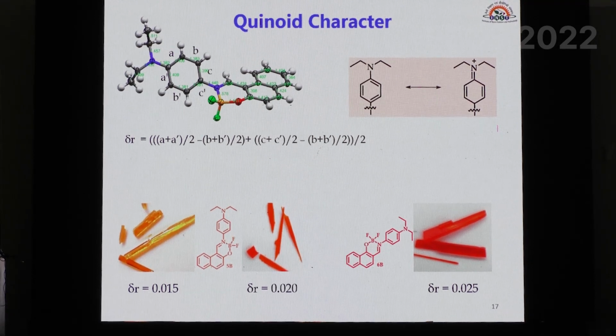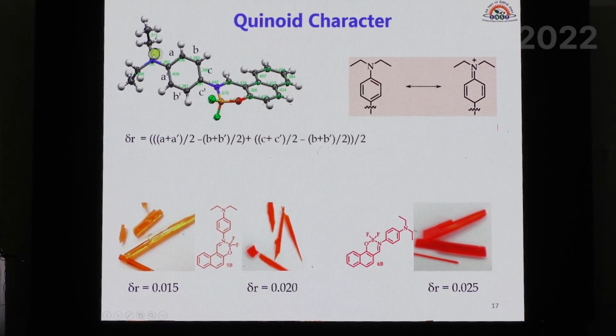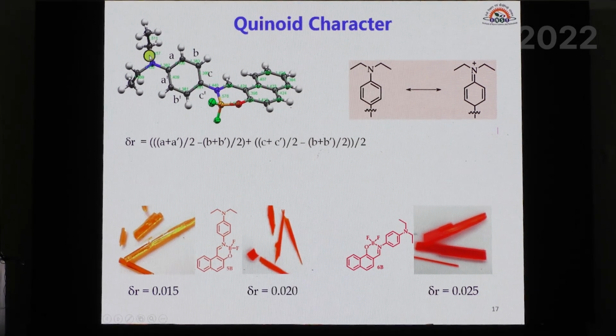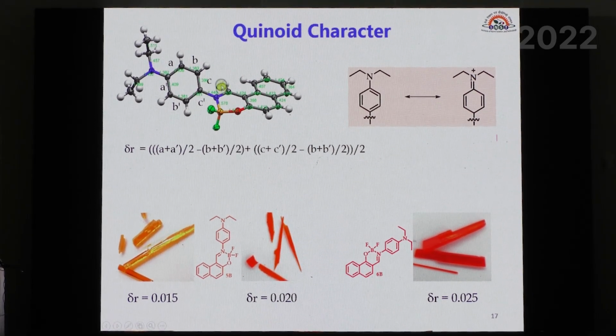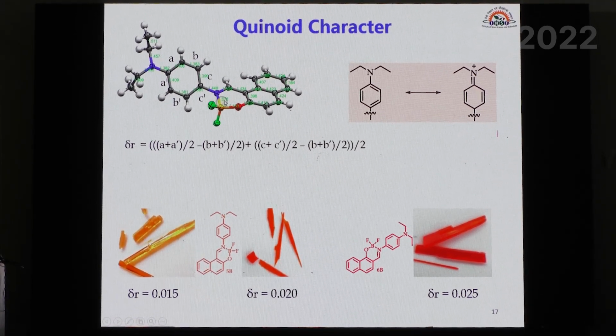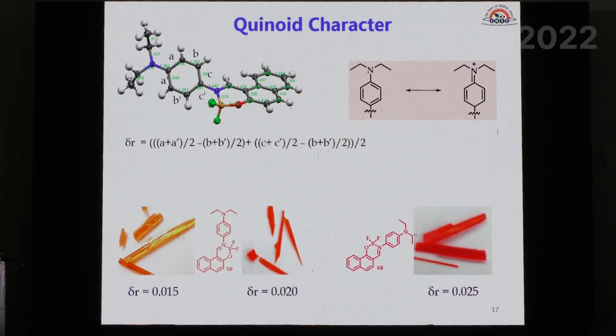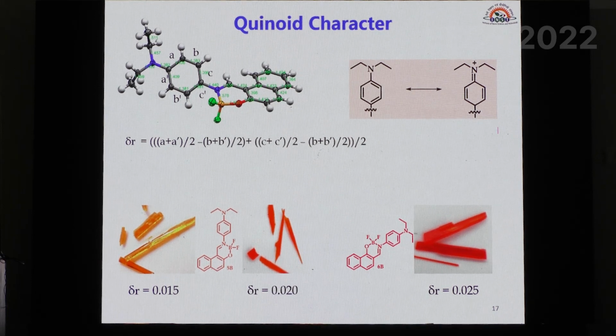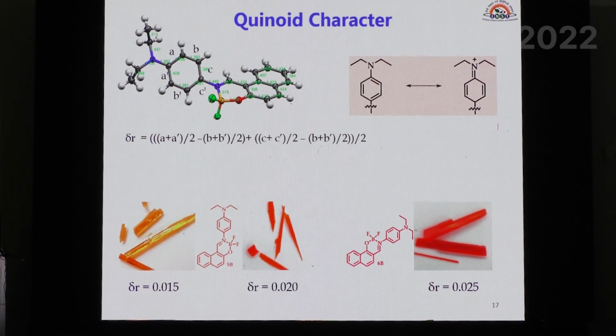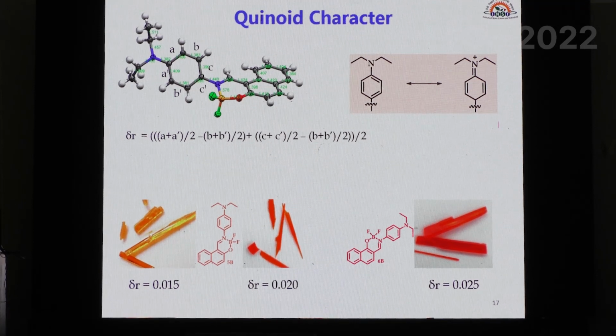Because of that, there is a strong interaction between the nitrogen, which has a lone pair of electrons, and this part here, where you have the boron, which is electron deficient. That interaction will be affected depending on the planarity of the compound, because conjugated molecules allow electron delocalization. Based on that, we can explain the difference in these properties.